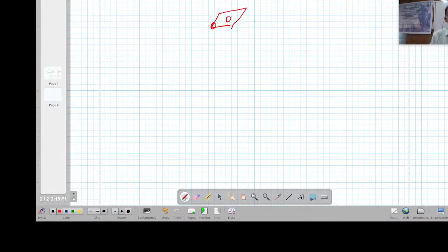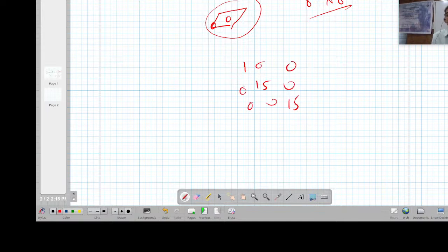Say, if I look at the two-dimensional cell, the graphene structure is like this. What if I want to do some doping? That means I repeat this cell 8 by 8, increasing the real space to 8 by 8, and then make some doping. Then there is no need to take, for the small primitive graphene structure, 15 by 15 as a K mesh. But if you are repeating it as an 8 by 8 cell, then your K mesh can be decreased.